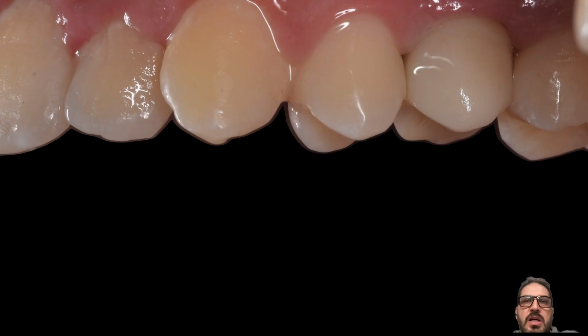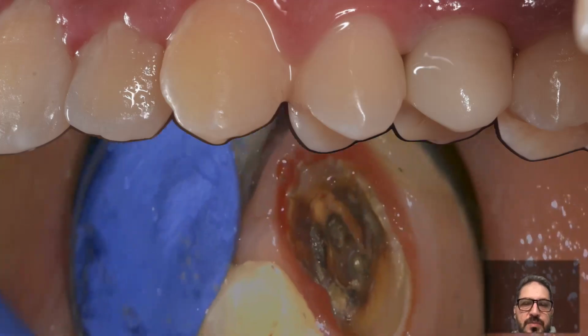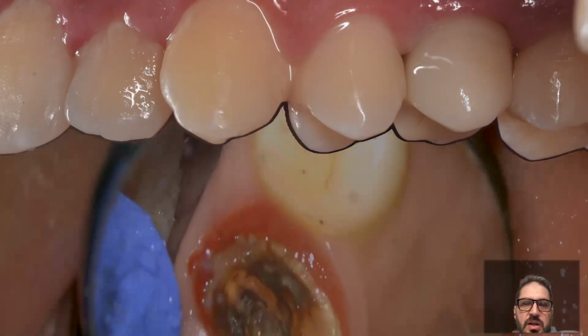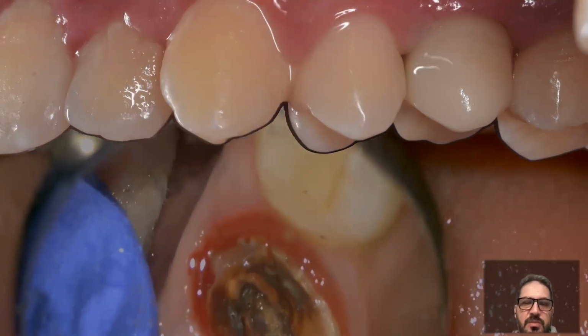Of course, we can do the same technique with metal post, composite, but everything is easier and more predictable now with hybrid ceramic, 3D printed. It takes nothing in our clinic, and in my point of view, it is more predictable to use a monolithic material as a post and core, not to make a material with a metal post, and it is not a 3D anatomical shape for the root. It's only a stock shape, which is round and full of cementation material around this round post. Remember the initial situation and what we can get from the restorations.